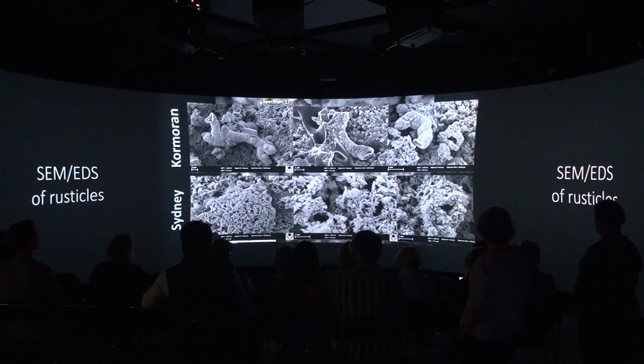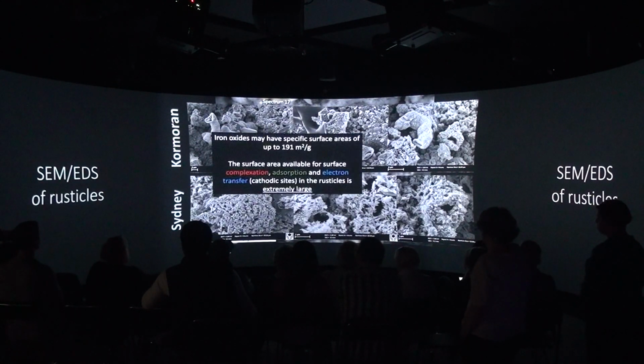they are really, really complex. You can see that they have a lot of specific surface area. These iron oxides, goethite, lepidocrocite, can have very high specific surface areas of up to about 191 square meters per gram. So this gives the rusticles an extremely large surface area for complexation, adsorption, and electron transfer.